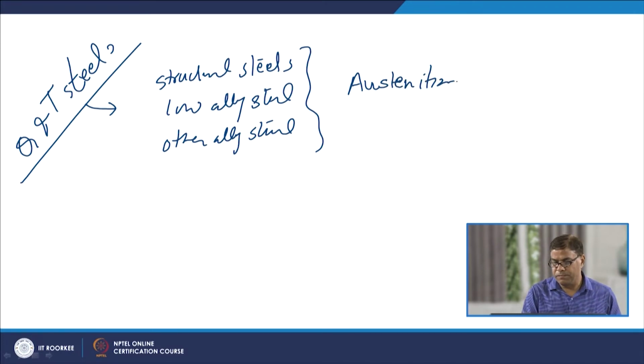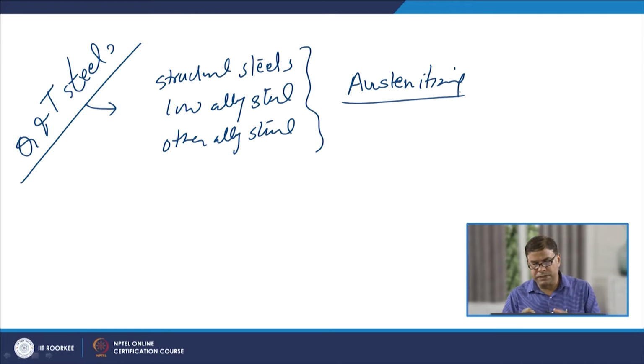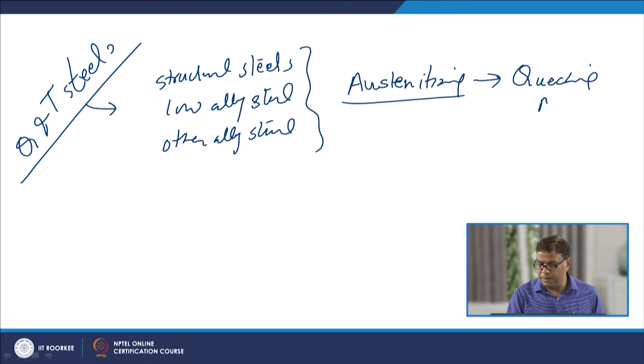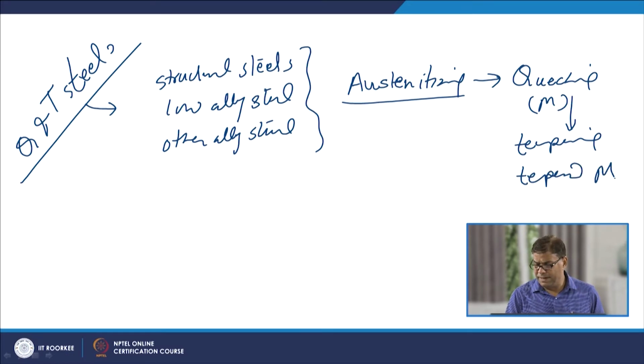austenitizing, means we have to heat it so that homogeneous austenite is formed, followed by quenching. So, that is involving the rapid cooling, and the primary goal of this quenching is to form the martensite, and thereafter the tempering is carried out at different temperatures as per the steel composition, so that the tempered martensite can be formed, and this combination results in extremely good